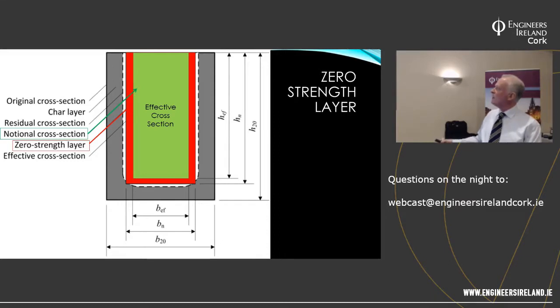Okay? Now, if we were putting thermocouples in the kiln in CIT, once it gets to 300 degrees centigrade, we determine it to be charred. But in reality, 7 millimeters inside that little red band, there's going to be a zero strength layer. There's very little strength. So you take 7 millimeters off on top of that. Now, research that's just been done last year shows that 7 millimeters is quite variable. It's 7 millimeters in the Eurocode, and that's what you can use. Obviously, the Eurocode is correct. However, it can vary between about 2 millimeters and significantly more than 7 millimeters, just out of interest, okay?